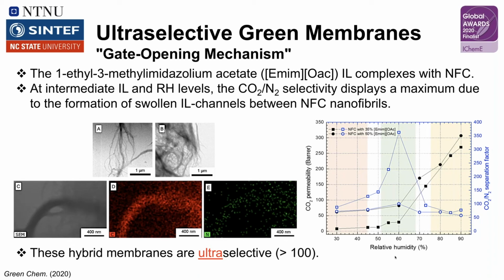These measurements are for mixed gases. It's important to realize that we're not just looking at CO2 and nitrogen. We're looking at a mixture of the two. And what we find is that in this range over here, that's colored somewhat salmon, we have a barrier type material that has relatively low selectivity as indicated by the separation factor. So these are based on measurements obtained from gas chromatography.